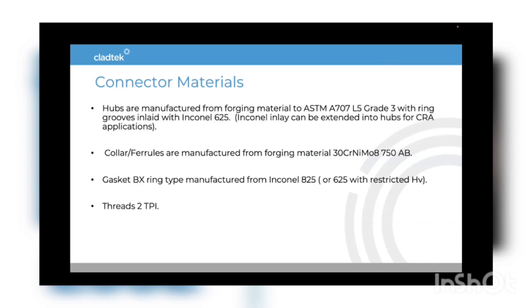So the connector materials, the hubs made from forging material, ASTM A707 L5 grade 3, with the ring grooves inlaid with Inconel 625. And if necessary, the Inconel can be extended into the hubs for CRA applications. And the CRA would then match up with a CRA liner, which would be slid from the pipe into the hubs and completed with an internal weld.